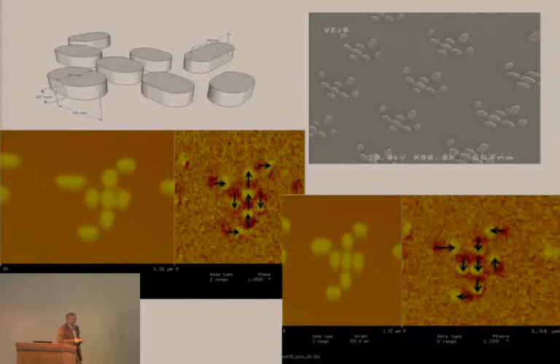We have also used shape anisotropy. In other words, different switching fields are required to switch dots with different aspect ratios and sizes in order to set one of these inputs for a majority gate. So here are the 3 inputs to this intersection. This dot here is a little bit longer. So in other words, it takes a larger field to switch it. And so you can see that for different input fields which we apply, we are capable of not switching this input dot, which is used to set the functionality, if you want, of this 3-input gate, whereas the shorter ones actually switch, and the majority gate switches as designed.